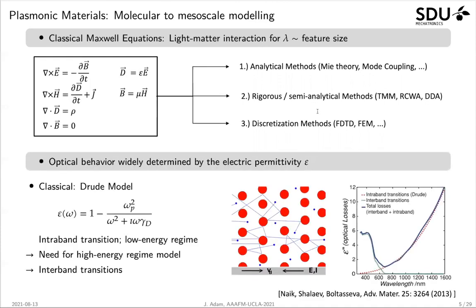How do we combine materials with these simulations? They are basically governed by the electric permittivity epsilon. Classically these can be modeled by the so-called Drude model, which covers mainly the intraband transitions, so they are valid only in the low energy regime. In the low wavelength regime there's nothing to represent the total losses of a material, and therefore you need Lorentz terms to cover the higher energy or lower wavelength region.